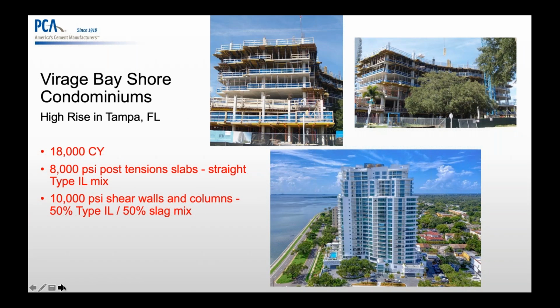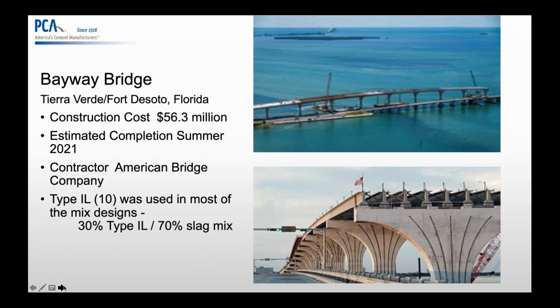This is closer to home now. In Tampa Bay, here in Florida, the Virage condominiums, a pretty important high-profile project, 18,000 cubic yards, straight cement mixes with Type IL cement, and even with slag 50-50 mixes, and a very successful project, very high profile.